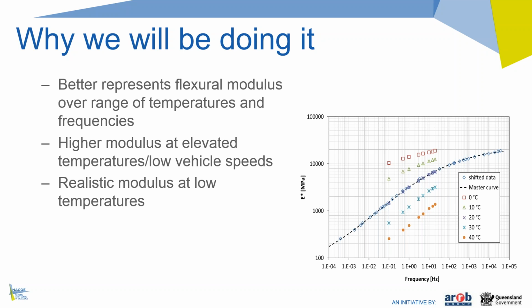So why are we doing that? Well, first of all, if you compare this to what we have been doing, we're running the tests over a range of temperature and frequency, and therefore we're better characterizing the material. And the master curve better represents the flexural modulus over a range of temperatures and frequencies compared to our current method.